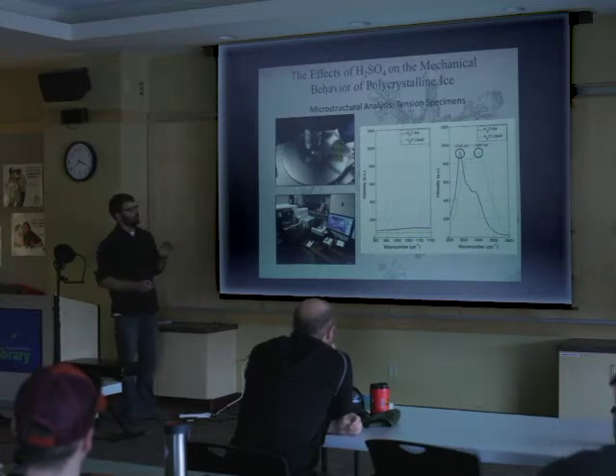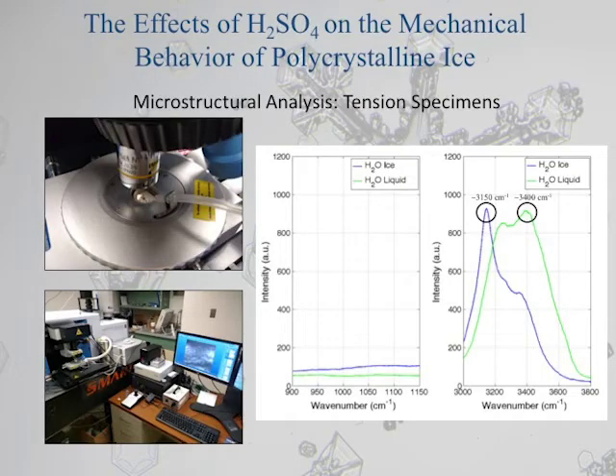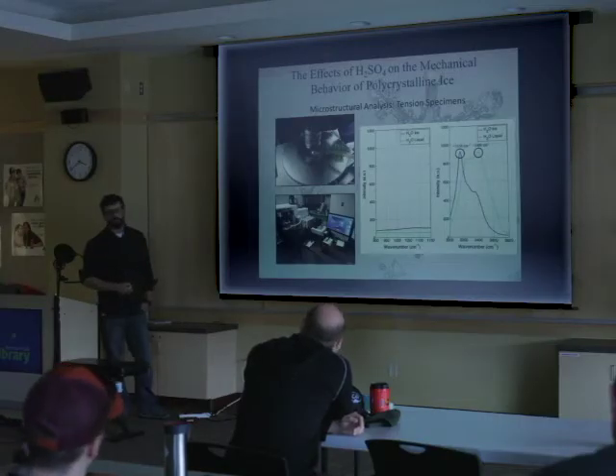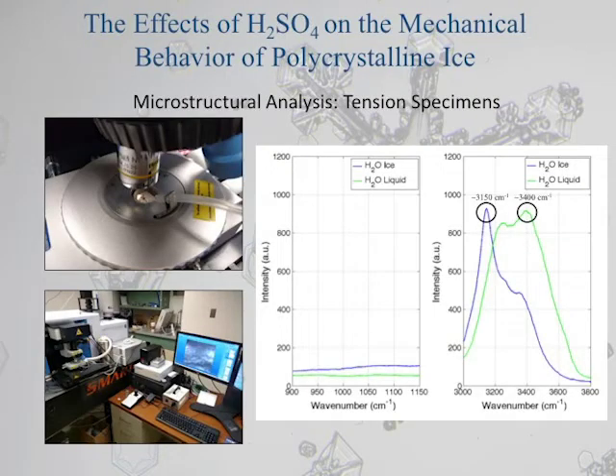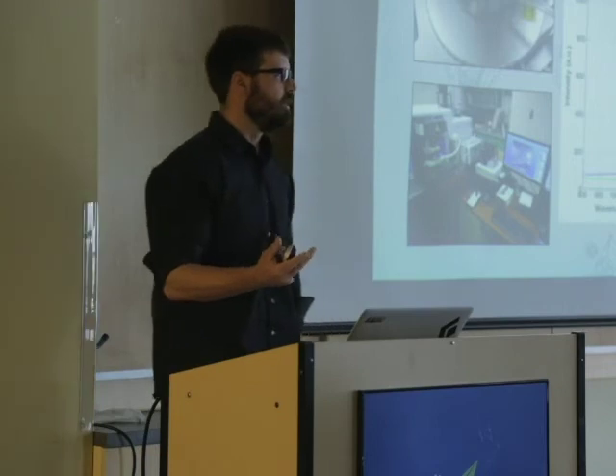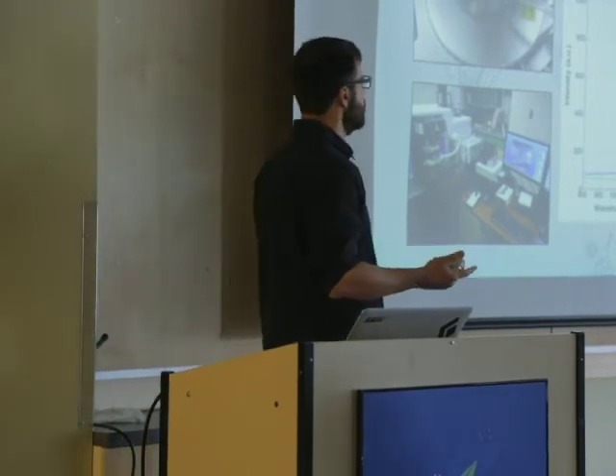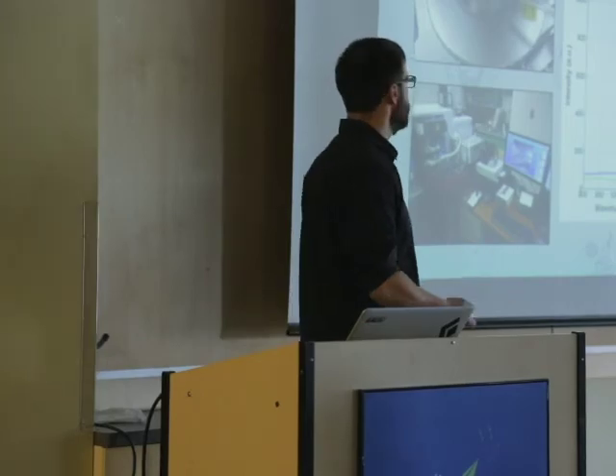So on the right here, I'm showing what it looks like for just pure H2O, water. There's a peak here for ice, and there's a peak over here for water. And this is due to the oxygen and hydrogens being bonded together and how they're stretching, how much freedom of movement they have. So you have a really obvious peak from the Raman for solid versus liquid. And then over here, you don't see anything. This is a flat line I'm showing on purpose, because if there was a sulfate molecule there, an SO4, you would have a peak right here. And obviously there's not, because we didn't add anything to this sample. But this is a tool that we can relatively quickly use to characterize where the sulfuric acid is in ice, and maybe even how much of it is there.